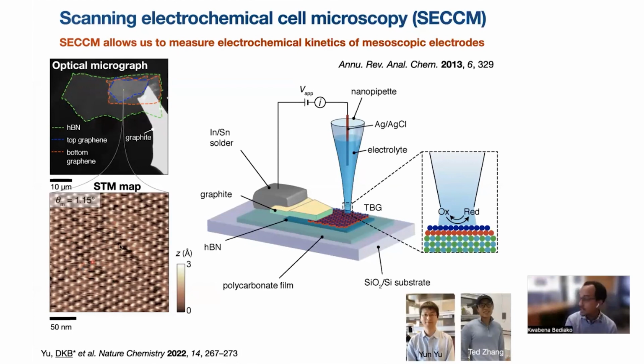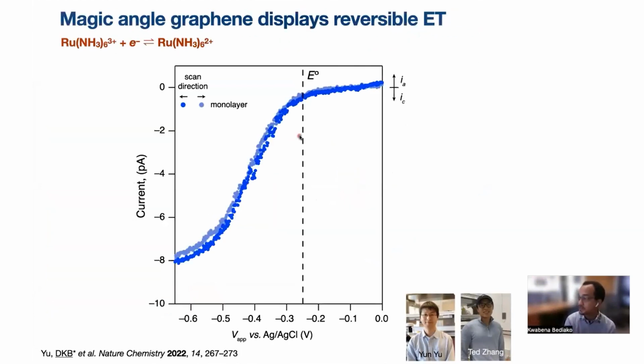So here we're probing the ruthenium 3+/2+ couple in this ruthenium hexamine redox reaction. If we were just to take a monolayer of graphene and sweep its potential, what we do see is this S-shaped curve, as we expect for this nanoscale electrochemical experiment, where the curve is offset from the equilibrium potential of our ruthenium 3+/2+ couple, simply because the kinetics of the reaction are relatively slow. We can understand this as arising from the fact that graphene has a low density of states. And so according to our Marcus-Hush-Chidsey model, we would expect that low density of states to manifest as a low rate constant, right? And so the kinetics are not as facile, and we have to pay a price in overpotential to drive the reaction.